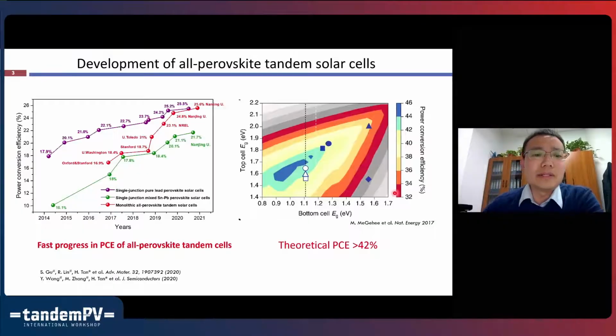In the past 5 years, due to the fast progress in single junction narrow band gap perovskite solar cells, the efficiency of all-perovskite tandems has also progressed very fast. A few months ago, our group published an all-perovskite tandem with an in-lab efficiency of 25.6%, which is very close to the highest reported single junction perovskite solar cells. But still, because the theoretical efficiency for tandem devices is well above 40%, we still have much room to improve the efficiency.